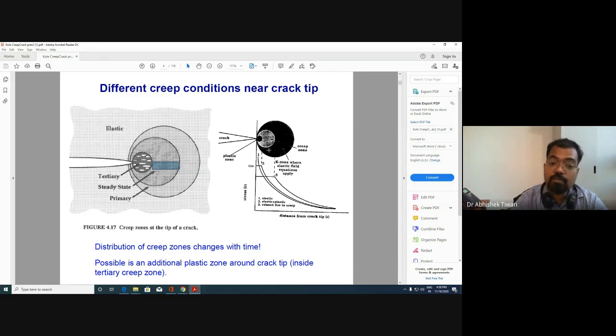So you will have plastic deformation, which is not time dependent, and time dependent deformation, which is creep deformation. So you can have both of these. Depending upon what temperature and what stress you are applying, you can have plastic zone bigger than creep zone, or you can have creep zone bigger than plastic zone. So you can have a small plastic zone, which is circumscribed by the creep zone, or you can have the reverse of that.